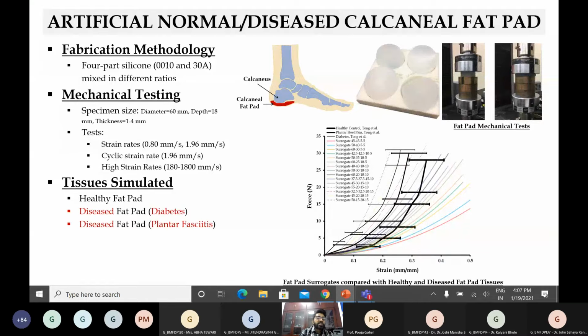So we came up with a fabrication methodology for a 4-part silicone-based mixture with different ratios to build this calcaneal fat pad. We had a certain specimen size, and this specific tissue would usually undergo compression, so we are testing in compression. We looked at different strain rates because depending on if you're walking or standing or running, this calcaneal fat pad will go through varying strain rates or varying ranges of impacts. So we looked at different strain rates to capture all that.